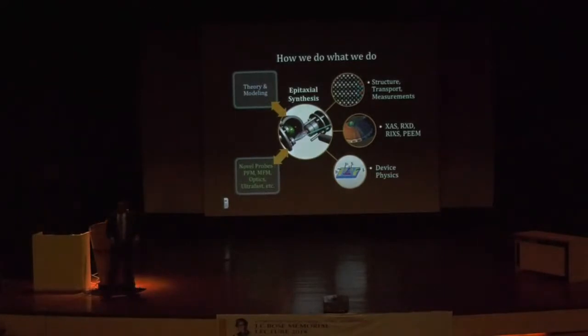How do we do what we do? We use epitaxy as a pathway. I was so excited to see all of the single crystal capability that you all have here. We make single crystals in a slightly different way. We grow it one atom at a time by MBE-like processes. We're also poor people, and therefore we use a laser MBE process rather than a gas source $3 billion MBE system. We use a $300,000 laser MBE system.